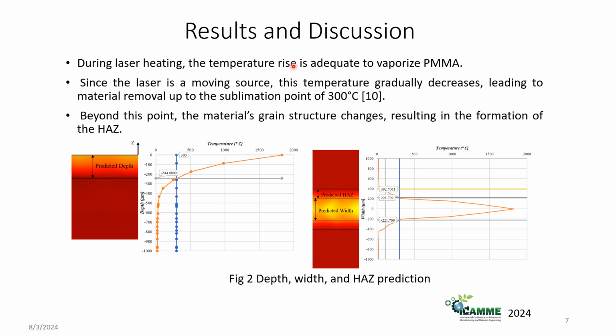During laser heating, temperature is adequate to vaporize PMMA. Since the laser is a moving source, this temperature gradually decreased, leading to material removal up to the sublimation point of 300 degrees Celsius. Beyond this point, the base structure changes, resulting in the formation of the heat affected zone. We can see in figure 2 the temperature profile towards the depth. When the material cools until it reaches 300 degrees Celsius, we get the channel depth, and this was calculated by the cut point of the temperature profile and 300 degrees Celsius.